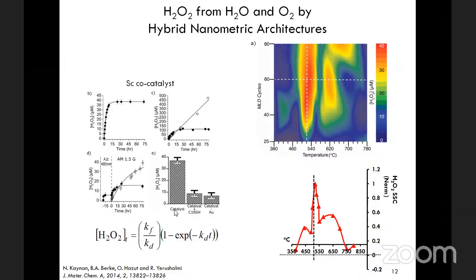If we use a co-catalyst, for example, scandium, one can get relatively high photocatalytic hydrogen peroxide production, as you can see here. This changes the kinetics of the catalytic reaction. And again, I want to stress that the hydrogen peroxide produced here involves no sacrificial compounds, and this is purely redox reactions of water and oxygen molecules dissolved. This is quite unique for titanium dioxide.